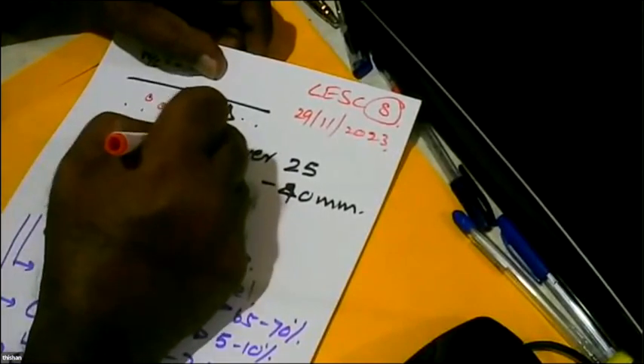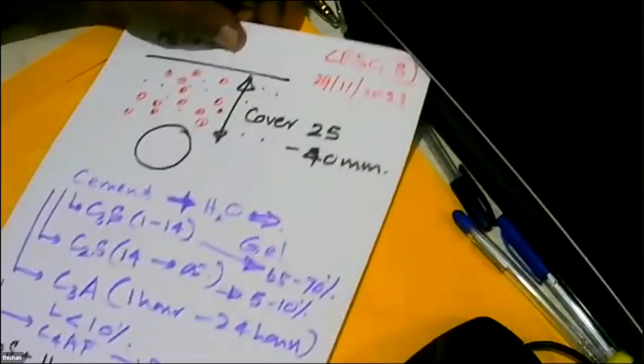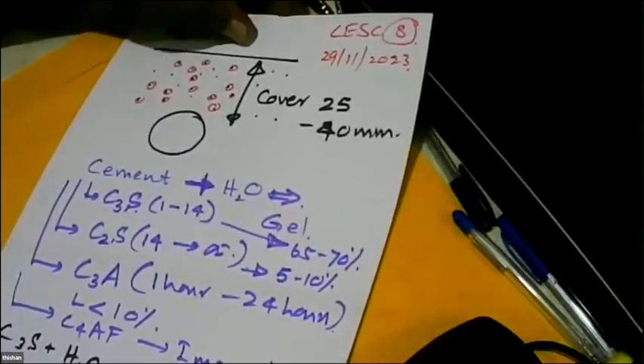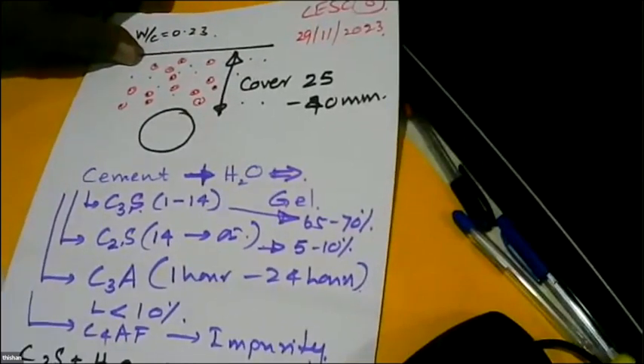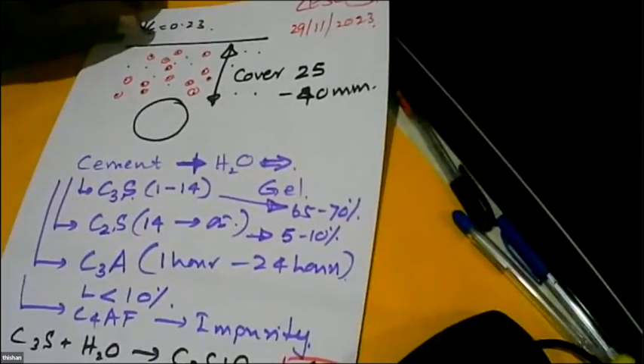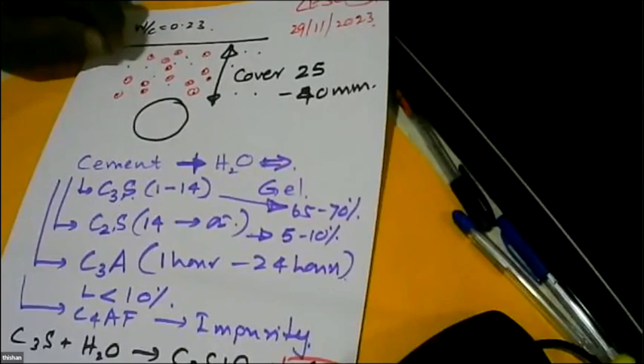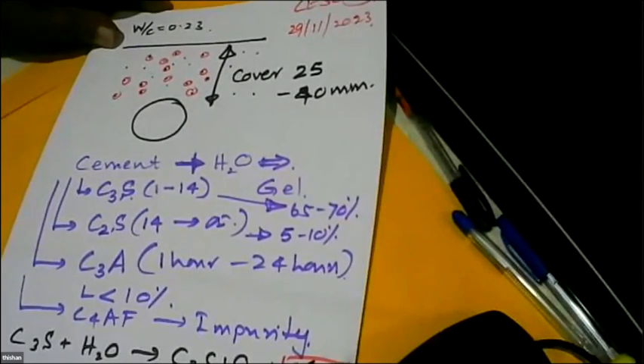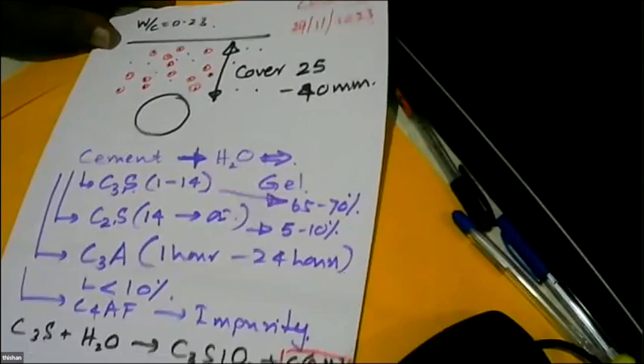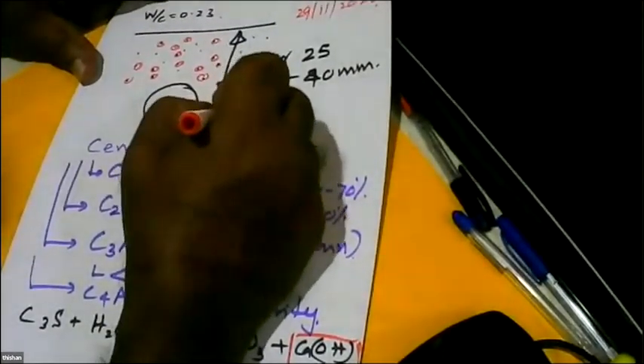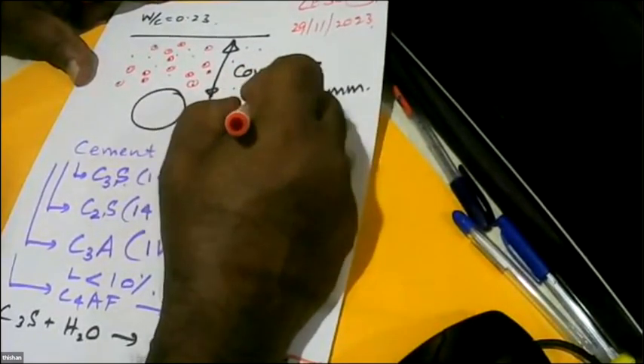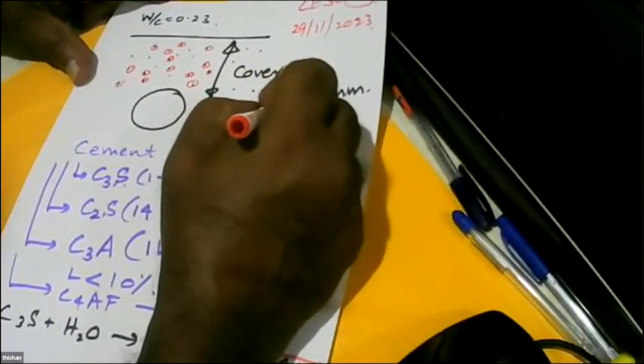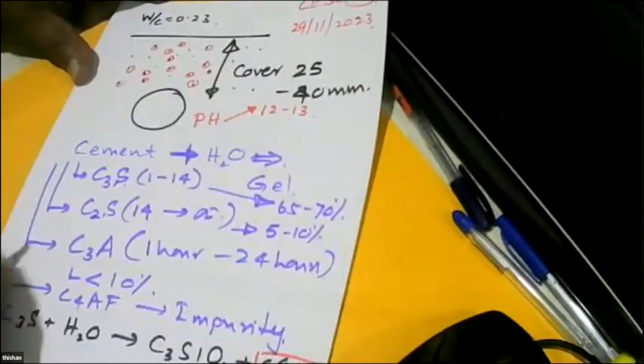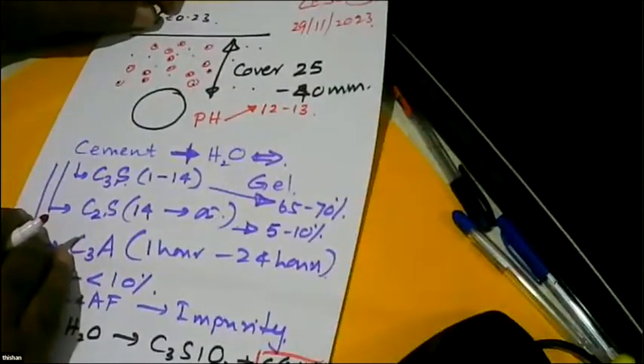So it's very important that we cure concrete because we are going to fill up all these extra voids with calcium hydroxide. That's why, when water flows over concrete, you get some whitish colored substance coming out, and that is calcium hydroxide, washed away. So we create calcium hydroxide, and it fills up those tiny pores. And calcium hydroxide, what is the pH? In well cured concrete, the pH can be close to 12 to 13. You cure it well. If you don't cure it, it can be less.